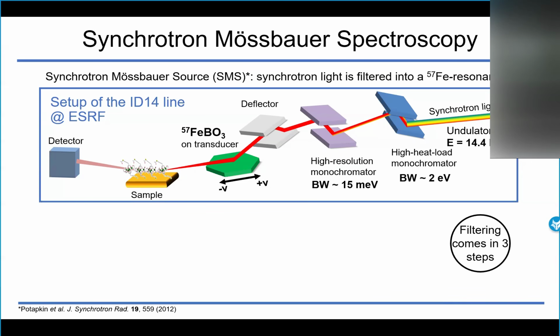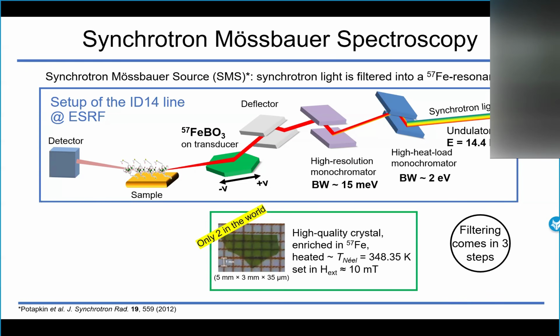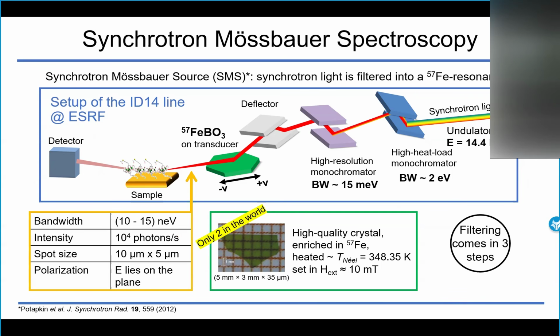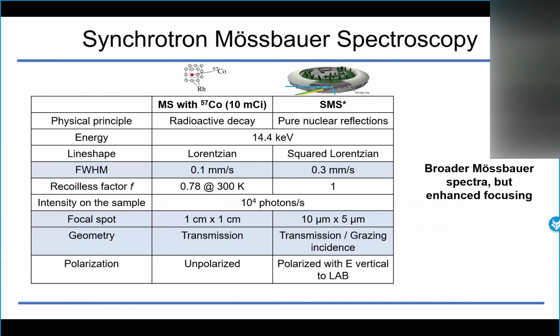First, by means of common monochromators. Then, by means of a nuclear monochromator, which is an iron borate crystal, a high-quality crystal that is kept in particular conditions of temperature and external magnetic field. In this way, it behaves like a nuclear monochromator, such that the radiation inside it does only pure nuclear reflections. So, out of this iron borate crystal, the bandwidth is around 10 nanoelectron volt, and the intensity is of the order of 10,000 photons per second. So now it is instructive to compare the specification of the synchrotron Mössbauer source with those of a 10 millicurie source in the classical setup.